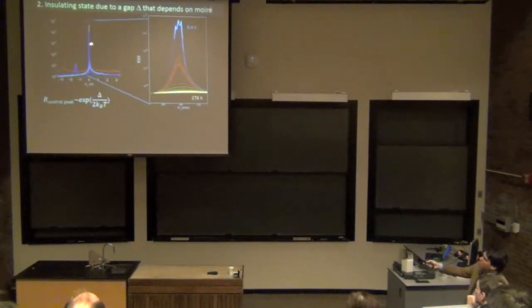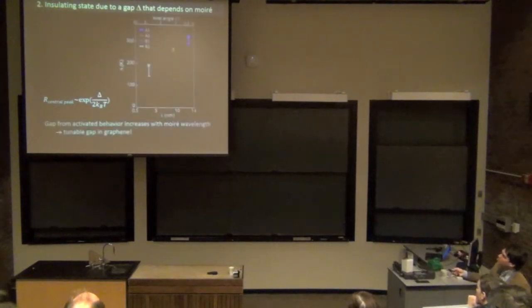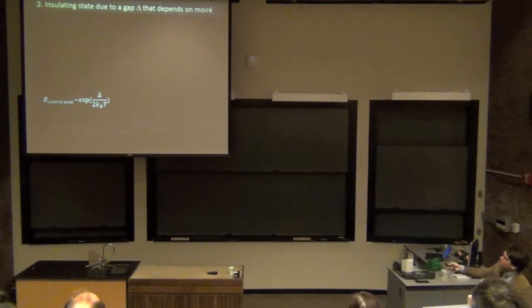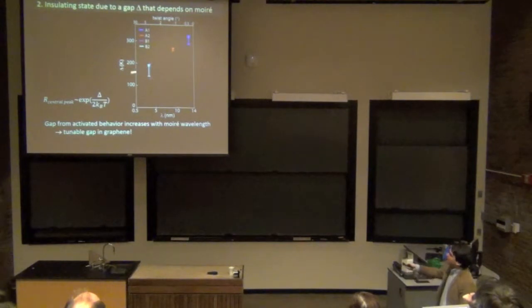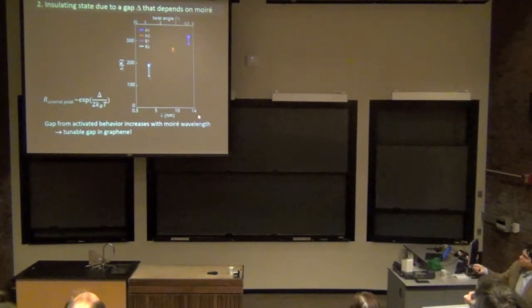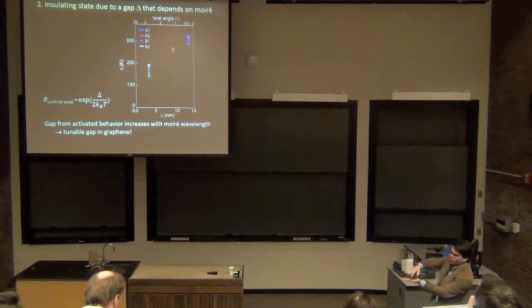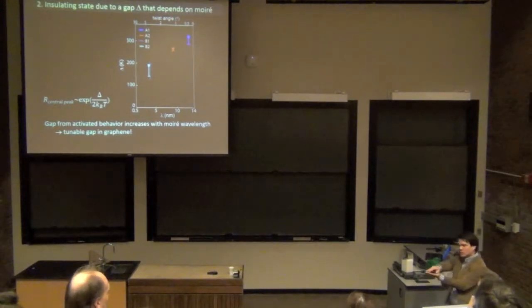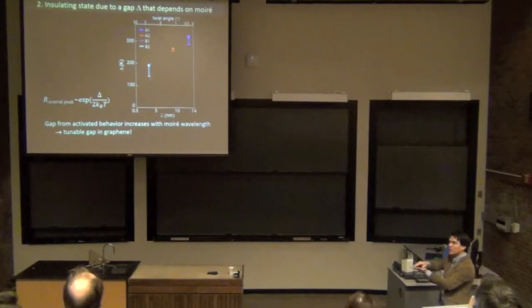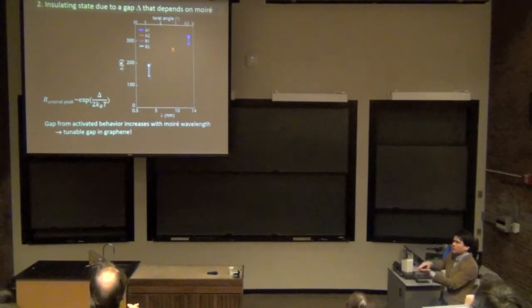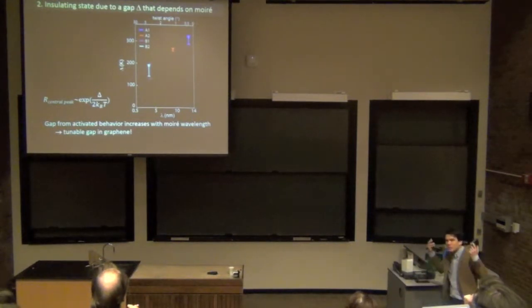What's going on with this huge resistance peak at charge neutrality? So you could do temperature dependence of this central peak here. What you find out is that it looks basically like activated behavior, that the resistance increases exponentially with decreasing temperature, which points to there being maybe a gap opening up in our system. And so we measured this gap, as deduced from these temperature measurements, as a function of the moiré wavelength. And what we found, and maybe this is the most important part of the first part of my talk, is that the gap that we measure actually increases as we twist the graphene layer closer to zero twist angle. So that fits with our intuition of the graphene and boron nitride being more strongly coupled at low twist angle. And as we twist away from perfect alignment, the gap goes down and we restore the intrinsic behavior of graphene.